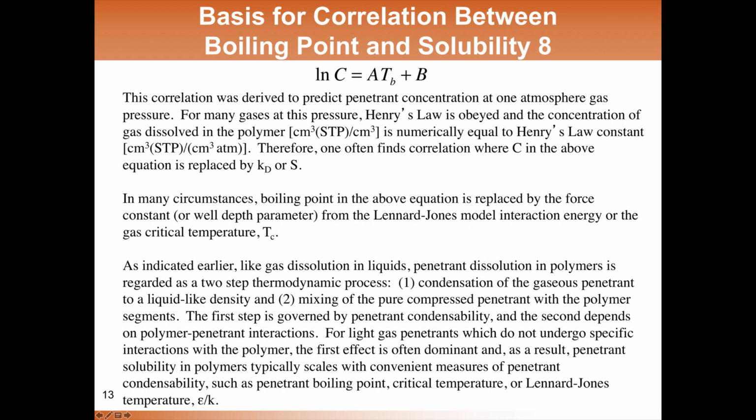And so just to reinforce the physical picture, the penetrant dissolution is regarded as a two-step thermodynamic process: condensation of the gaseous penetrant to a liquid-like density, and this is the large step from an energetic point of view, and then mixing this pure compressed penetrant with polymer segments. And if this first step is dominant, then solubility will follow a very simple relationship with critical temperature of the type that's shown at the top of the page.